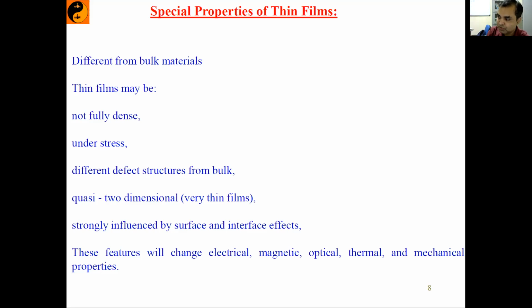Besides that, the surface is also very important in thin films, because suppose your film thickness is, say, 1 nanometer, then in your material mostly your system is either only interface or only the surface. There is not much left as far as the bulk is concerned. So we know that at the surface, many of the coordinates actually change considerably. The surface energy is entirely different with respect to bulk.